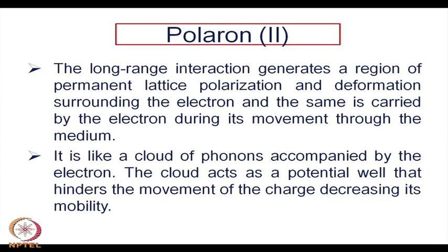So, it is also the mobility which determines the overall conductivity, and the polarons, because of the polarization associated with them, are as if a much larger species is moving within the medium, and therefore its mobility is much less, and it has different interrelations, different characteristics so far as the mobility is concerned. So, this is all about polarons. We will not go into much more detail.